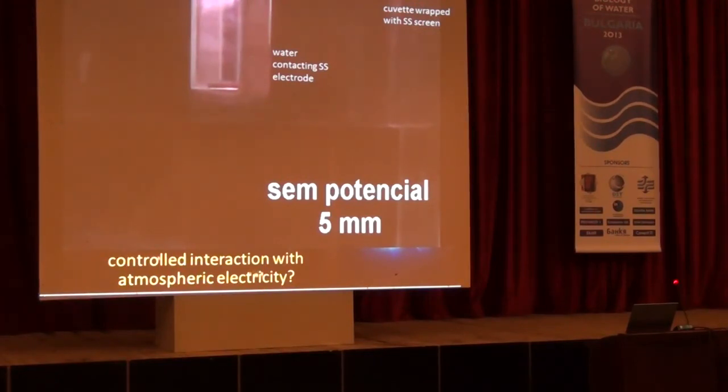When you go to higher humidity, the overall surface potential decreases, both positive and negative. But when you compare the changes in potential from different pixels, you see that there is no evidence of charge transfer by any surface mechanism. So in many cases, we can see a pixel with very positive potential.